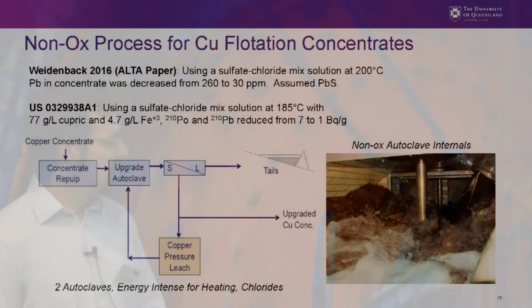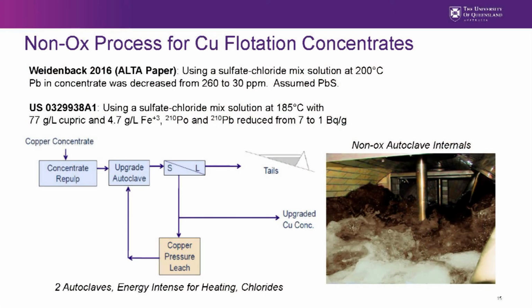This type of process has been used previously for separating copper from nickel, related to nickel smelting processes in South Africa. And so it is conventional technology in that sense, but it has yet to be applied for treating copper concentrates. So there's a recent patent where they're using mixed sulfate chloride solutions at about 200 degrees, and they showed in this conference paper how lead in the solid phase was decreased from 260 to 30 ppm. And then in the related patent, there was another example at 185 degrees with this starting solution, 77 grams per liter copper in solution. And in this patent, they showed how polonium-210 and lead-210 were reduced from 7 to 1 becquerel per gram.